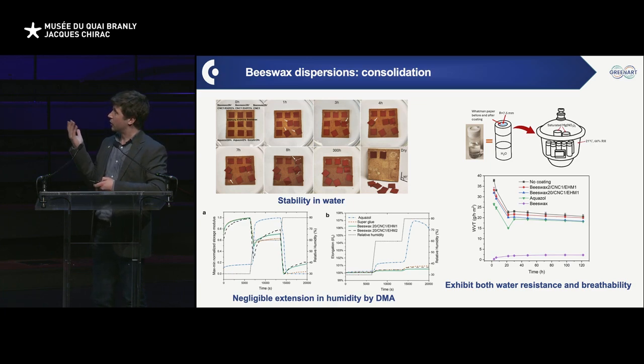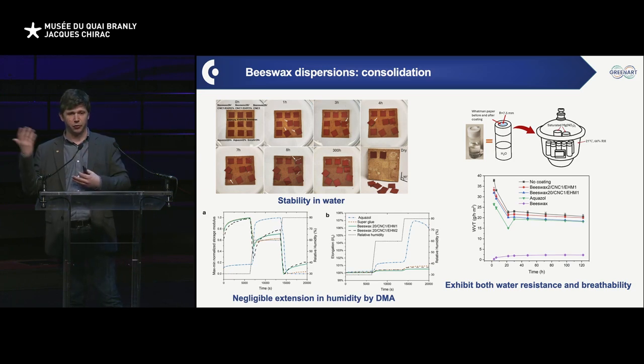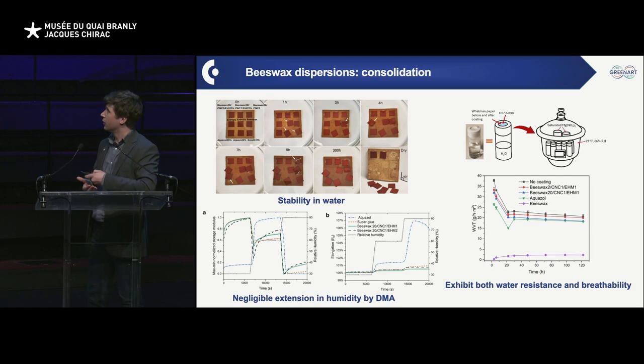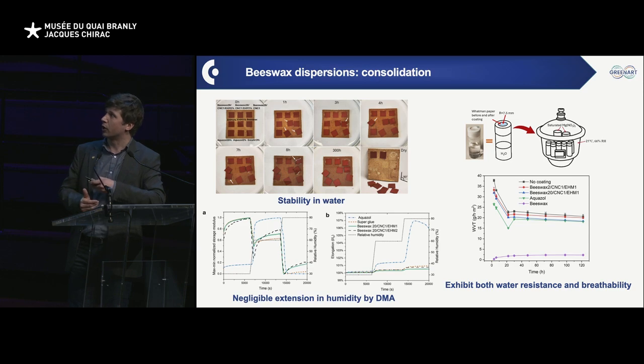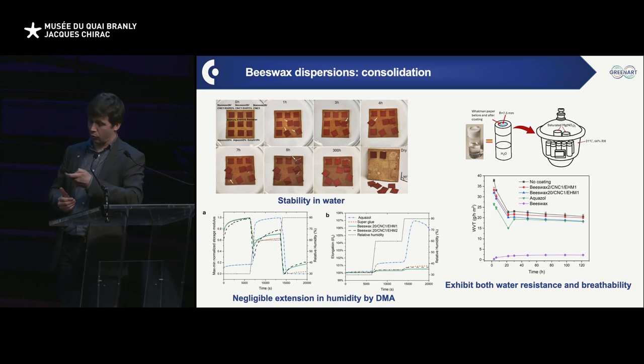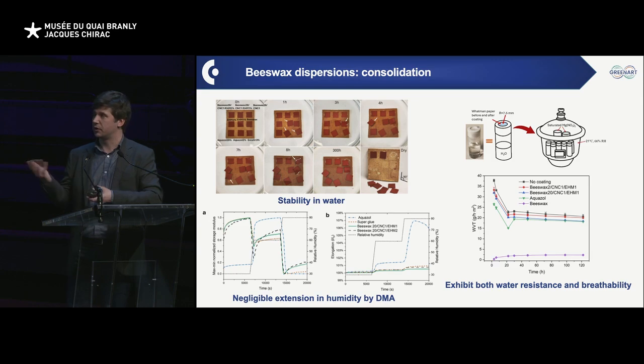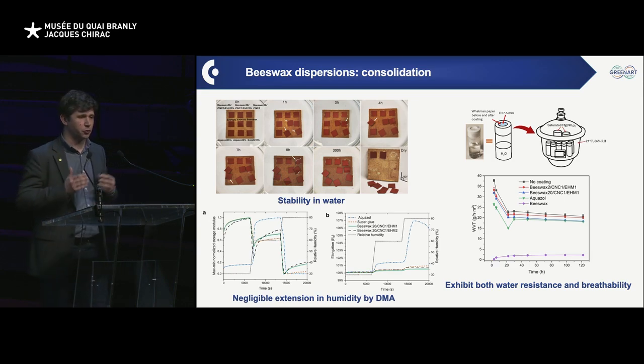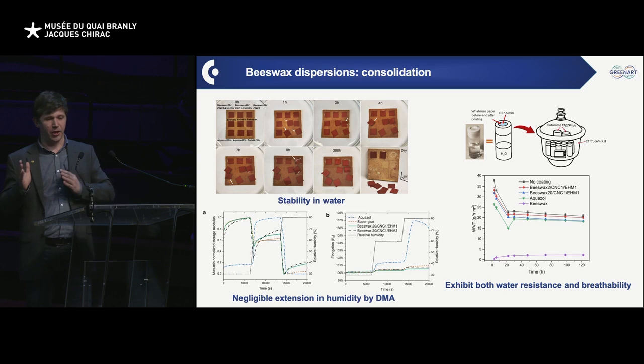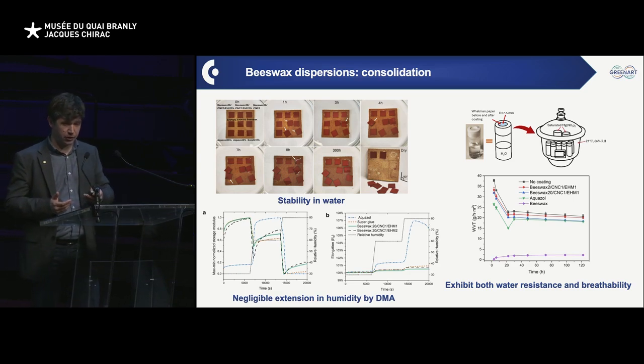At the same time, we were happy with that. We thought, okay, we need to be able to demonstrate that the system has this breathability that we thought we had. So we did water vapor transport measurements. This is a pure layer of beeswax, so nothing goes through beeswax essentially. And when you compare with our formulation, you can see that we have a decrease at the beginning over the first hours, but then it stabilizes and remains pretty constant. This is most likely due to equilibration of the system. So that means we have both water resistance and breathability, which was actually pretty great.